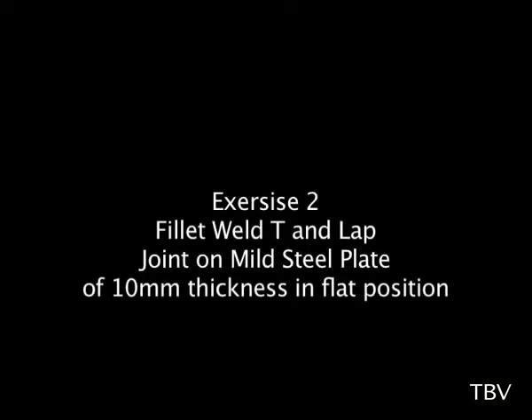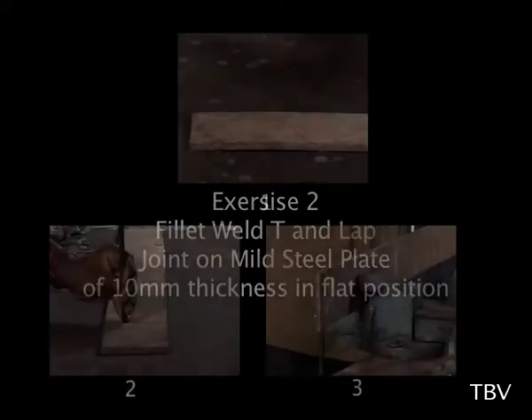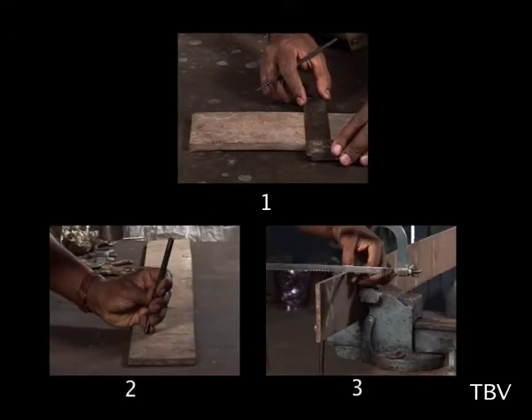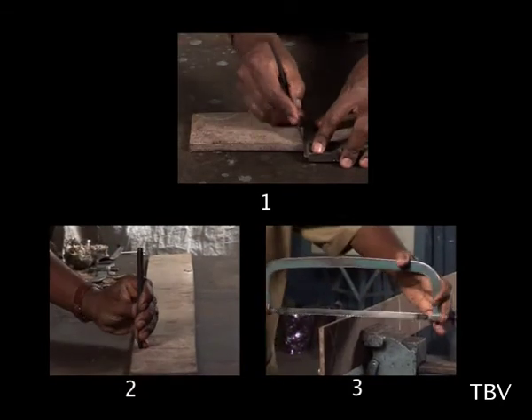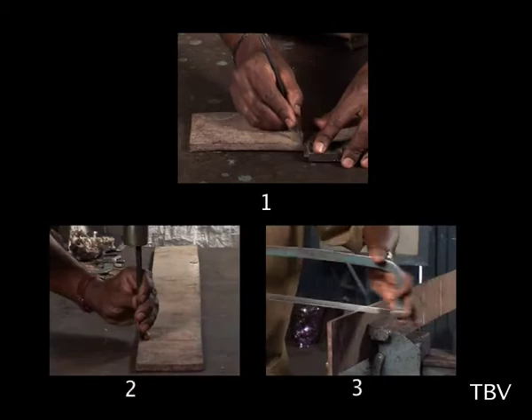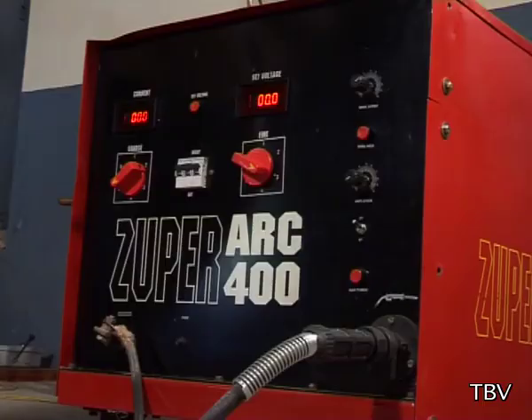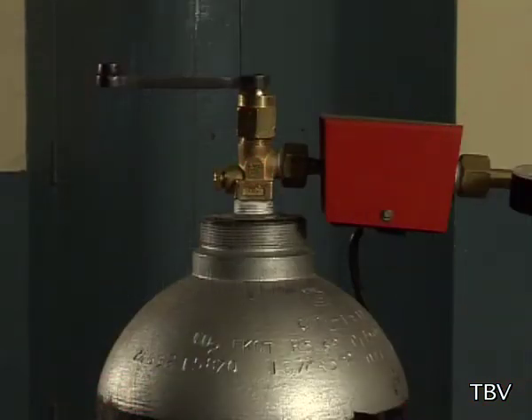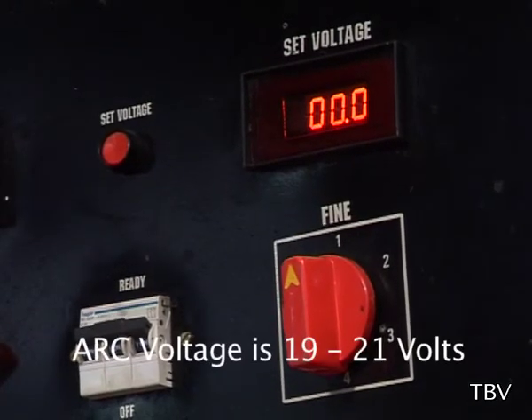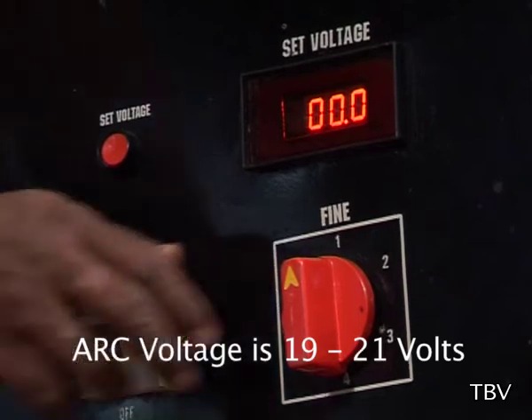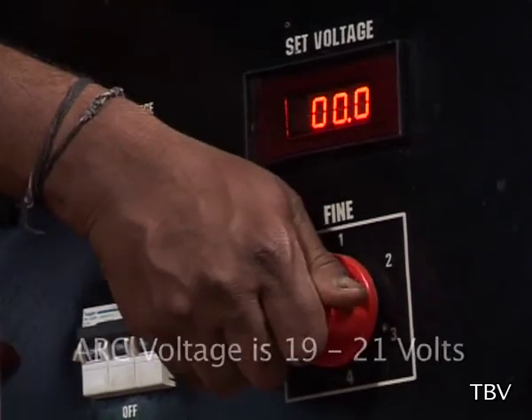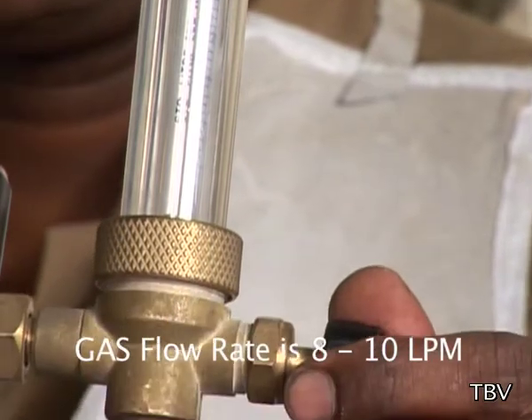Exercise 2. Fillet weld T and lap joint on mild steel plate of 10 mm thickness in flat position. Mark the required dimensions on the mild steel plate as you did before. Now, the workpiece is ready for welding. The welding machine is on. The carbon dioxide gas heater is also on. Arc voltage is set at 19 to 21 volts as required for dip transfer mode. Gas flow rate is 8 to 10 LPM.